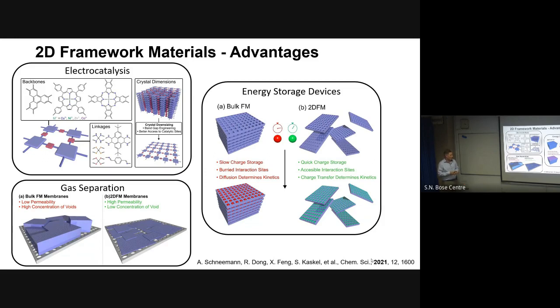And for energy storage devices like supercaps, this is expected to have much quicker charging. The interaction sites are better accessible, and in the most ideal case, the charge transfer is dominated by the redox kinetics and not by the diffusion kinetics within the bulk of the material.